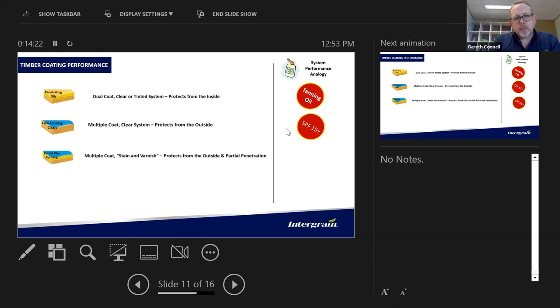Then we start talking about the multiple coat partial film forming systems. These are the modified water-based oils. These products provide a little bit of penetration within the timber, but also some external protection. You could pretty much regard these as SPF 15 plus type products, bearing in mind that both film forming clears and partial film forming products do contain pigments in them. In some instances with the clears, might I add, the clears do actually have a small component of pigment within them. Usually you'll see a yellower tint to the clear coat. This is purely there to provide long-term colour retention to the timber. If we didn't have that, the timber would actually grey underneath.